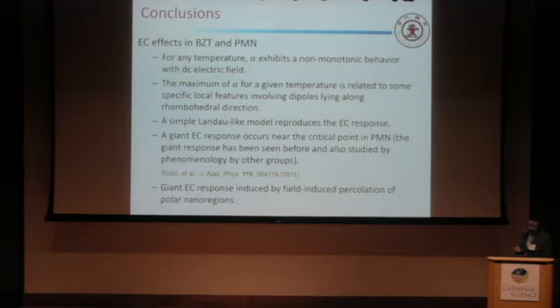The last is the conclusions, the EC effect in BZT and PMN. First, for any temperature, alpha exhibits non-monotonic behavior with DC electric field. The second is that the maximum alpha for a given temperature is related to a specific local feature, which is dipoles along different rhombohedral directions. The third is that we use a simple Landau-like model to reproduce the EC response. The fourth is that a giant EC response occurs near the critical point in PMN.